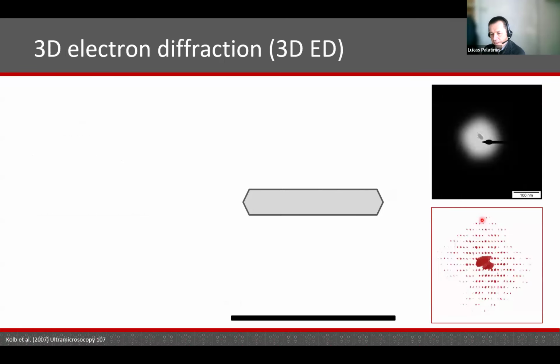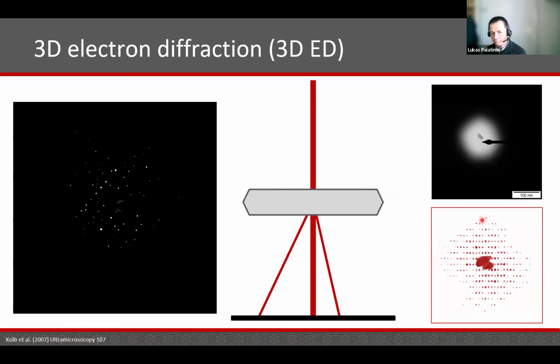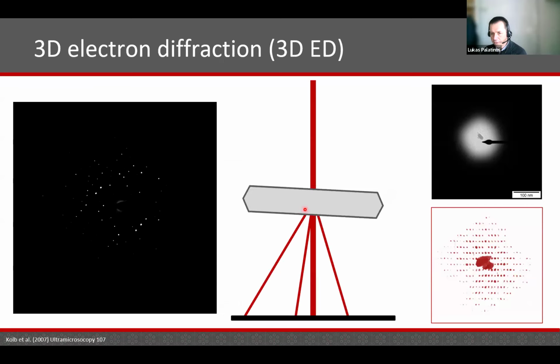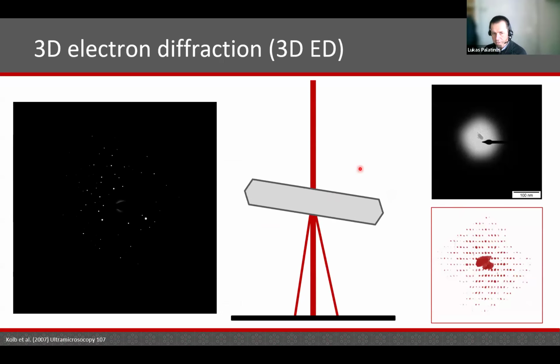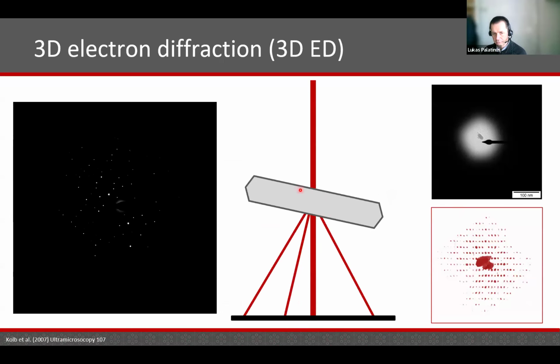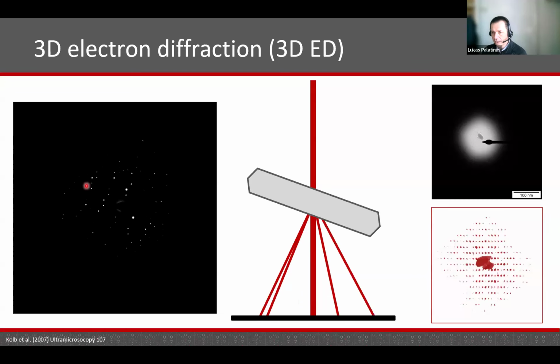The principle of the technique is very simple. It's very similar to X-ray diffraction data collection. So we take a crystal without particularly orienting it in the beam. We shine a beam of electrons through it, and then we rotate the crystal either continuously or in steps and record the diffraction patterns as the crystal rotates, as you see here. And then as a result, we can obtain a three-dimensional reconstruction of the diffraction space or reciprocal space, and well, that's then hence the 3D electron diffraction method. So the principle is very simple.